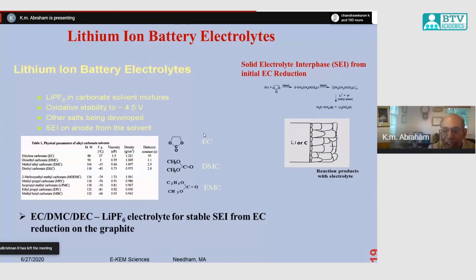So in order to dilute that, people put in other carbonates, the low melting point carbonates like diethyl carbonate and ethyl methyl carbonate, because the battery has to operate over a wide temperature range. It has to operate from minus 20 degrees centigrade to 80 degrees centigrade. So you cannot just use one solvent, ethylene carbonate. You need to find other solvents that will widen the operating temperature range of the battery. So you use a mixture of these solvents. That's a proprietary thing.